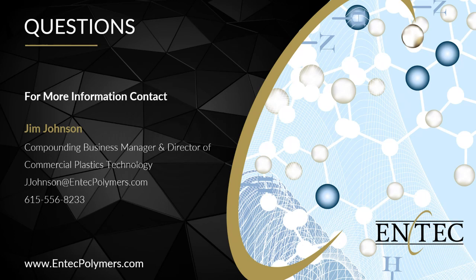If you have a PET and PE with a low percentage to compatibilize, could it be the same as if you have the opposite? Yeah, so if you had, for example, 95% PET and 5% PE, or you had 5% PET and 95% PE, yes, we would use the same compatibilizer. In this case, once again, I would use a glycidyl methacrylate modified material as that compatibilizer. The difference here would be if it's mostly PET, we could probably use lower levels of that compatibilizer. But if we had PE with large levels of PET, we'd need to use more. If we had the large levels of PET and low levels of polyethylene, we could use a lower amount of that.